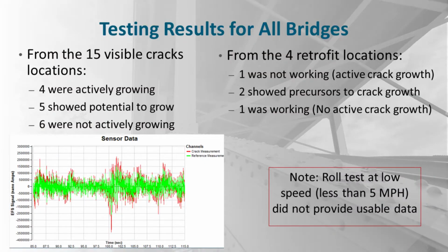And then we have the results from the retrofits. The first retrofit was not actually working. It showed that the crack was still actually growing, so the repair did not work. 2 of the other repairs show microplasticity, meaning it had a potential to grow, sorry. And only one of them actually was fixed. Out of these retrofits, the first one was a weld retrofit. The two that showed microplasticity were drill stops, and the last one was a cutout, the one that seems to work.